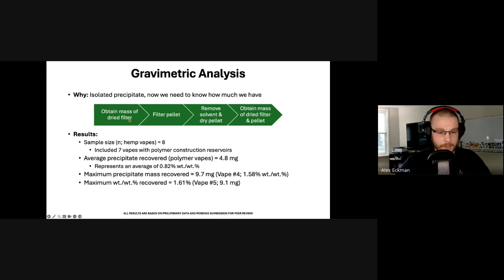I will note that ahead of time, an 8 vape sample size, 7 of those being polymer construction reservoirs. They were of the disposable vape type, and that was just obtained through a local CBD vape shop. The average precipitant recovered of those 7 polymer vapes was 4.8 milligrams, representing an average weight by weight percent basis of